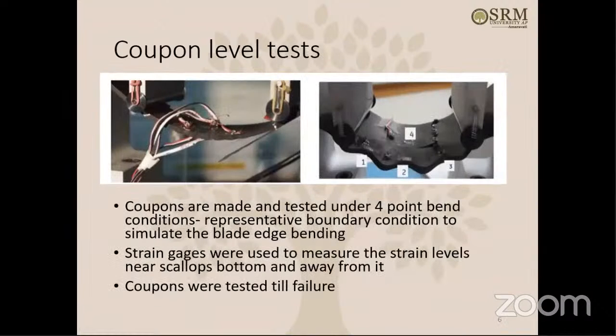As you can see, we fabricated the coupons, took them to the lab, and did this 4-point bending test. So why bending? Because, as we talked about earlier, under the bird strike load, the blade is going to bend lengthwise and widthwise also. So we are trying to create a similar boundary condition, a similar loading condition, that these coupons are subjected to: they are bending. Under bending, the small wavy features show a different response than the bigger wavy shapes, because when you bend the blade with bigger wavy shapes, they do not bend symmetrically. They go up and down, and the failure also happens differently.